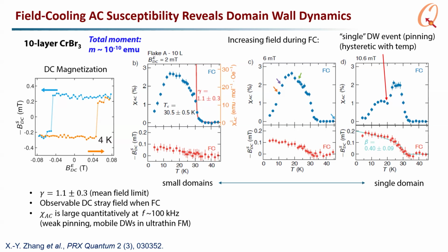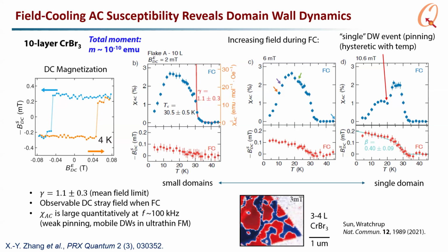In the case where we have small domains, we first have the initial paramagnetic to ferromagnetic transition, where that coherent AC rotation is first picked up, given by a critical exponent, which we find to be around 1, same as mean field. Then below TC, we essentially have domain wall motion, so domains getting bigger or smaller as a function of the AC field. But even so, in the strong field cooling case, because we have a very point-like sensor, we can be sensitive to just a single domain wall. If a single domain wall pins and then depins as a function of temperature, we can get kinks, a non-monotonic behavior that's sensed by the NV center.